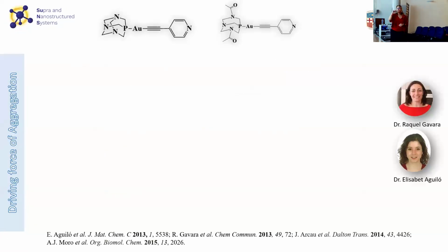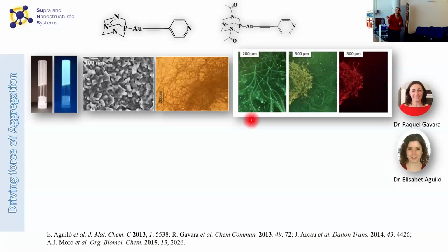Okay, I would like to explain to you a little bit about the aggregation with our compounds. As I explained before, some of the results that we started with were a little bit of serendipity. In these cases, we synthesized these simple molecules that contain exactly the same chromophore as I was explaining now, but with these phosphanes. And these phosphanes are soluble in water. So we wanted to see if the presence of these water-soluble phosphanes can induce the solubility of the systems in this polar media. But what we observe is that they self-assemble, giving rise to these hydrogelators, giving rise to the formation of these very long fibers that are also emissive. So we were not expecting the formation of these weak interactions in such a strong way, to such an extent.